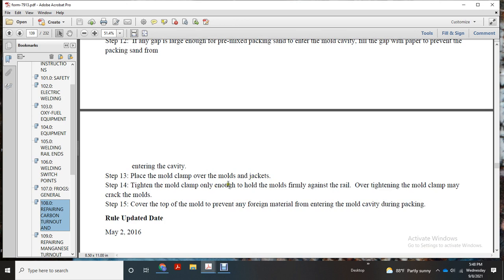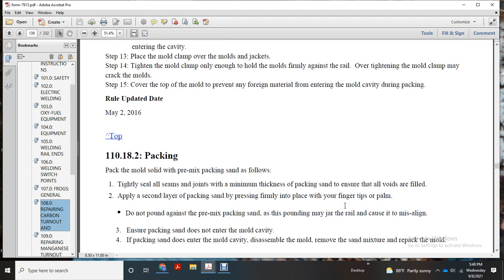Tighten the mold clamp only enough to hold the molds firmly against the rail. Over-tightening the mold clamp may crack the molds. Cover the top of the mold to prevent any foreign material from entering the mold cavity during packing.